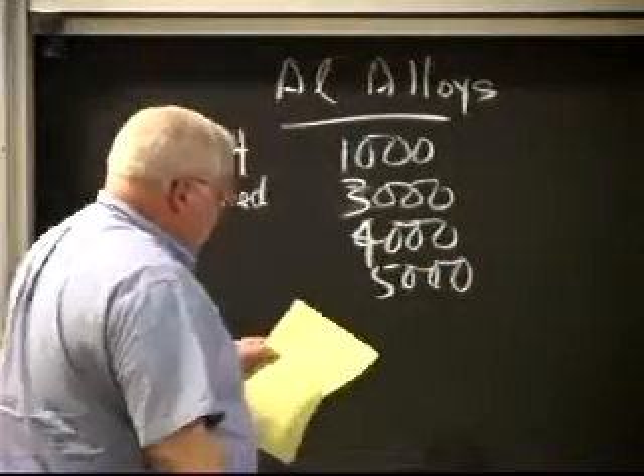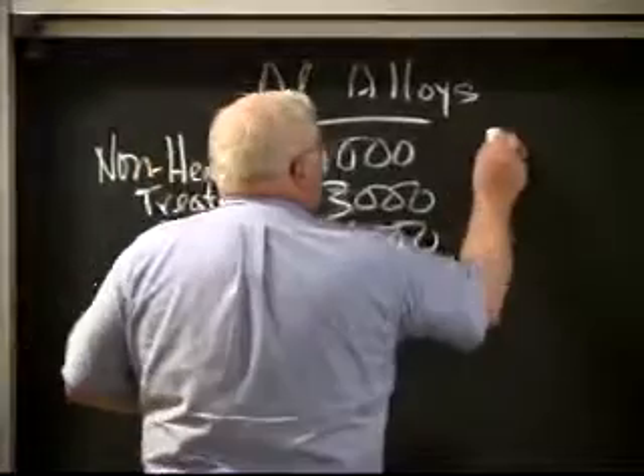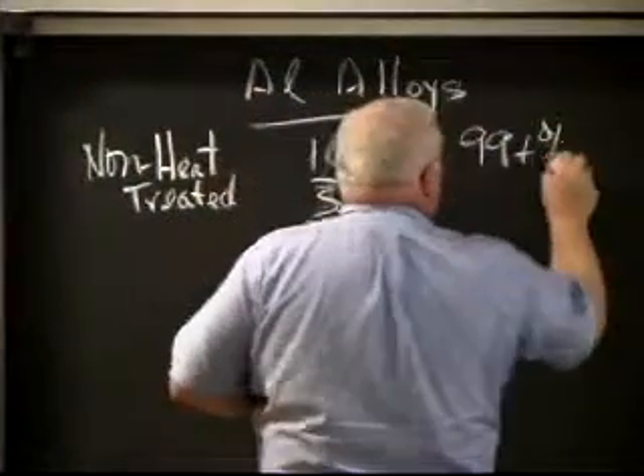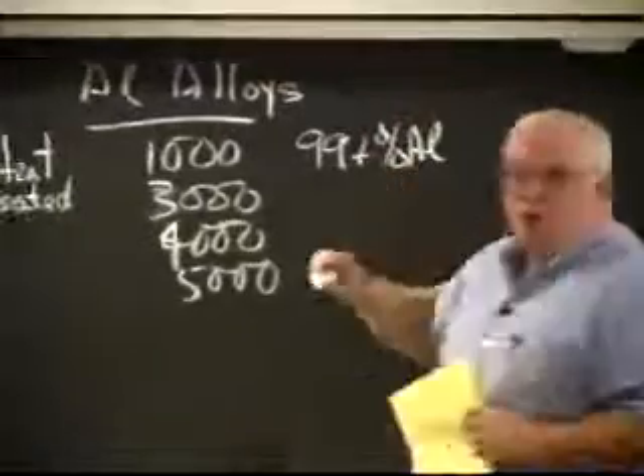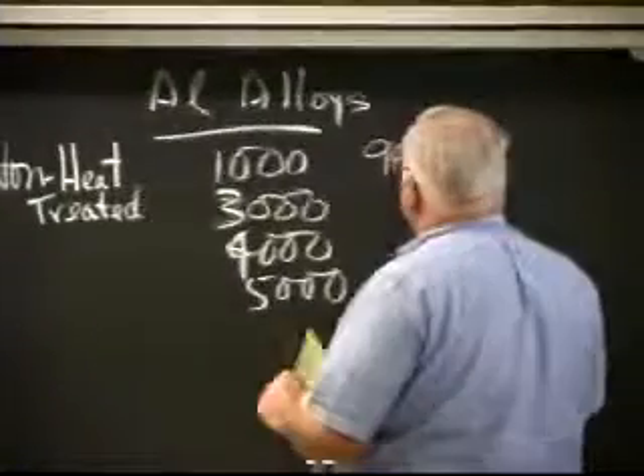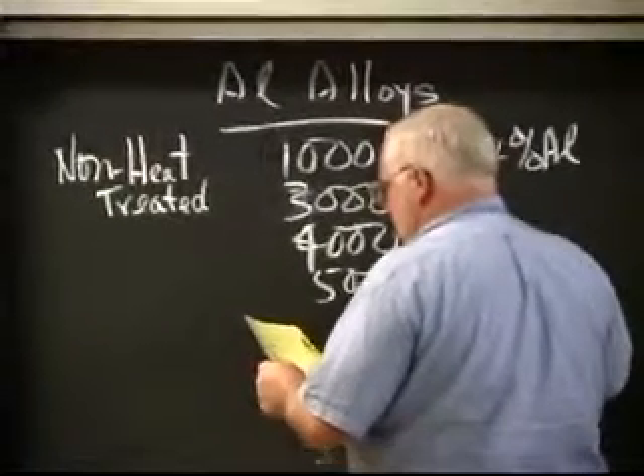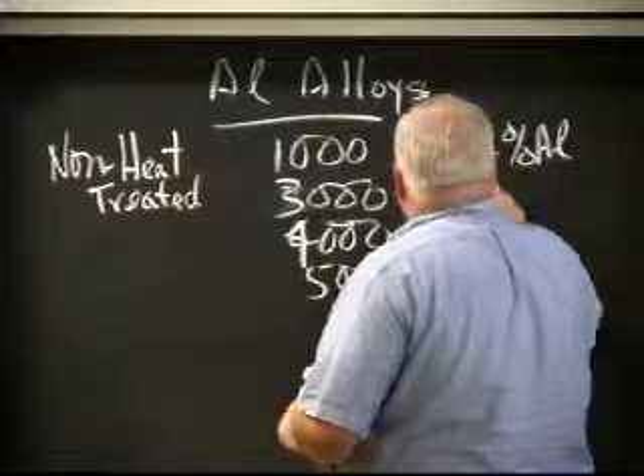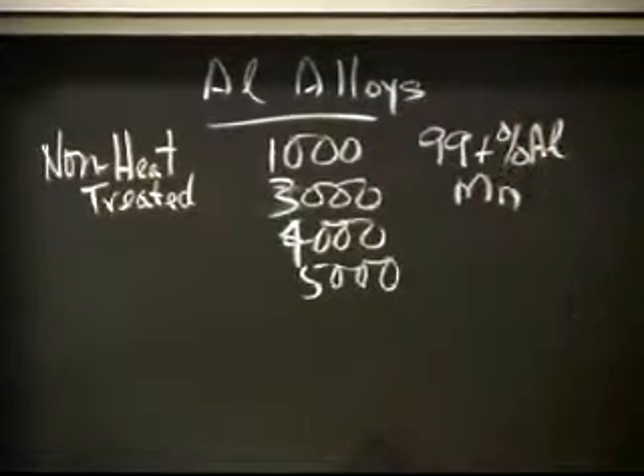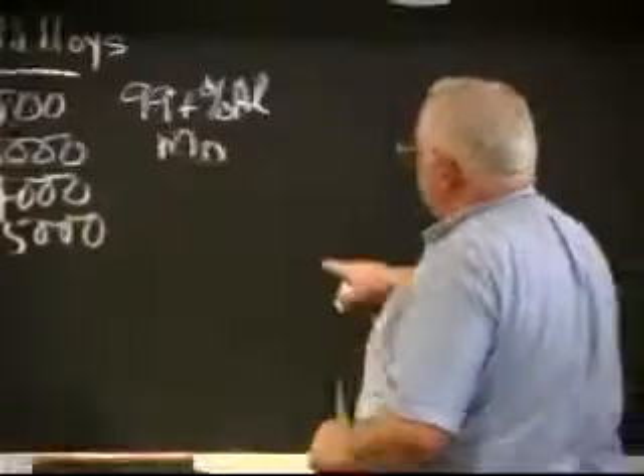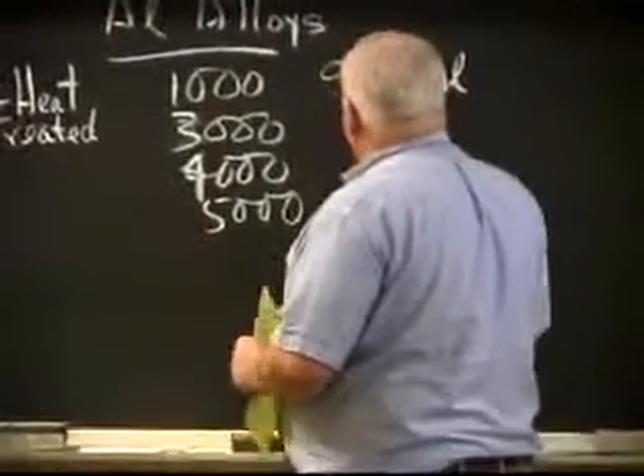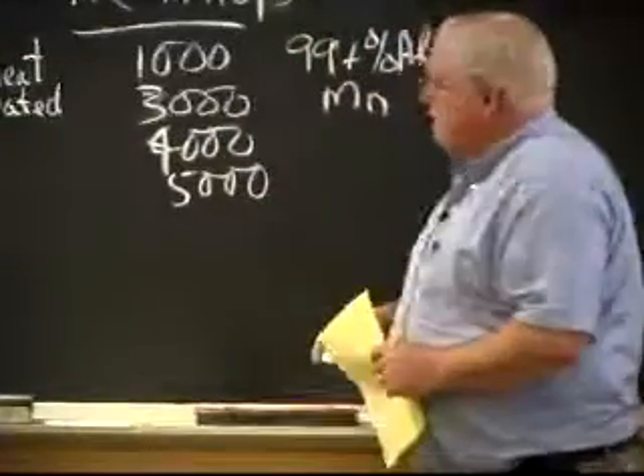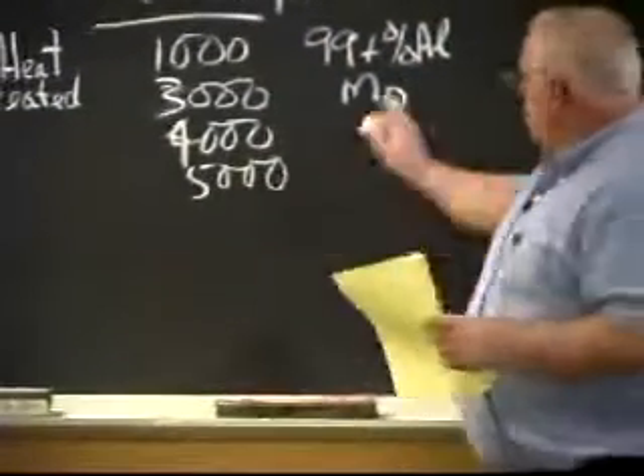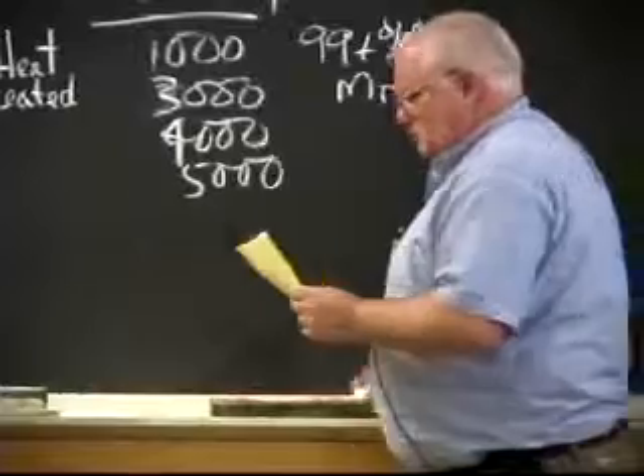And this is a designation from the Aluminum Association. The 1000 series are 99% plus aluminum. Good for aluminum foil, good for electrical conductors. We do use them as electrical conductors because they're cheaper than copper. The 3000 series are alloyed with manganese, used for beer cans, Coke cans, a few other applications. The manganese adds a little strength to what is otherwise a mostly aluminum alloy. So these 3000 series alloys, usually 98% aluminum, but you add 1 or 2% manganese to increase the strength.